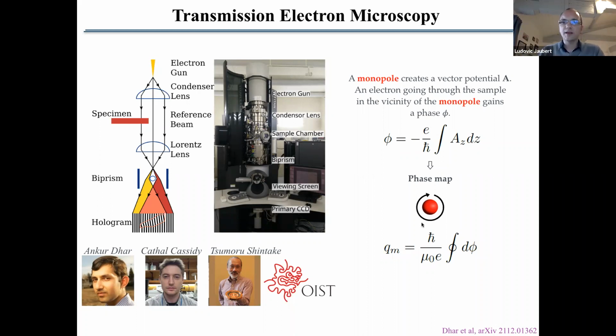this magnetic charge. And since you can measure this phase phi at the end, if you integrate around the singularity, around the magnetic charge, if you integrate this phase phi around this closed contour, this is a singularity, and so this will take a finite value, which will correspond to the magnetic charge with the proper coefficient in front of it. So you see that with electron holography, with an electron beam going through it, you can see the phase shift due to the magnetic charge, and you can measure the magnetic charge of the monopole.